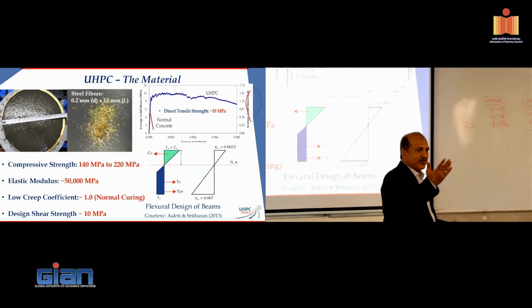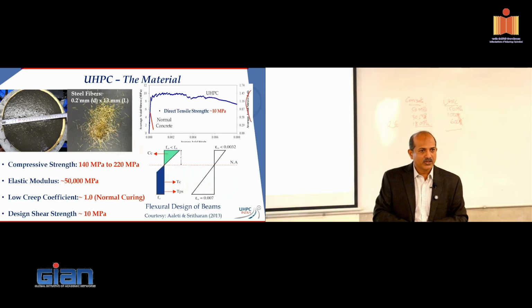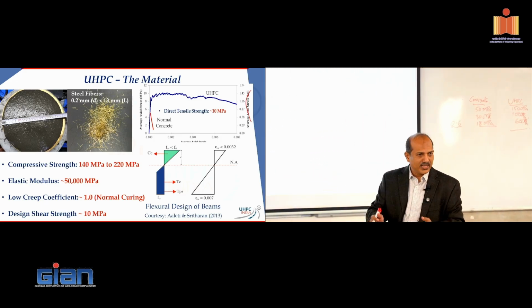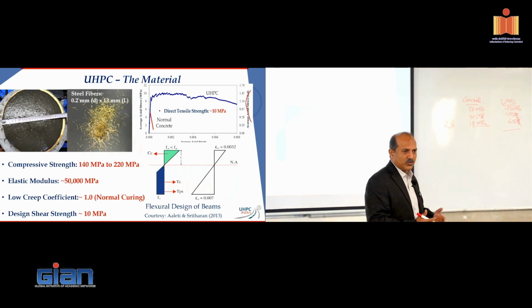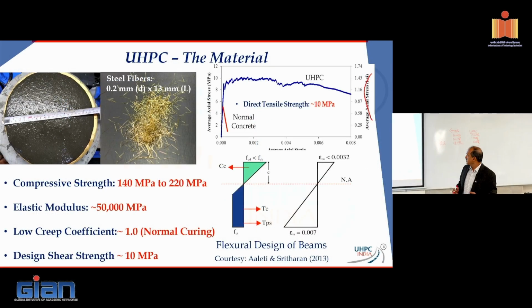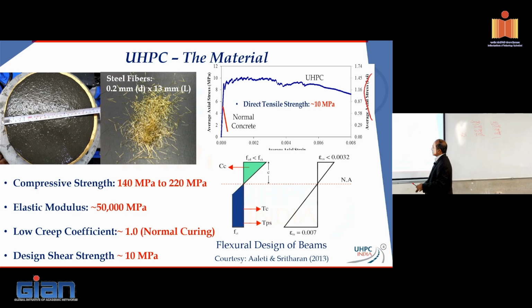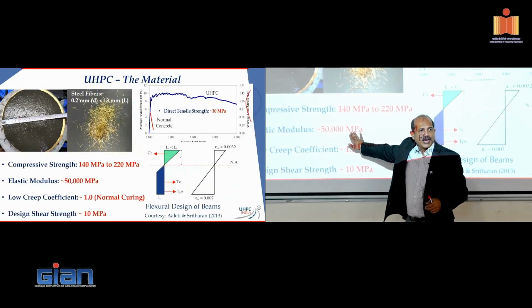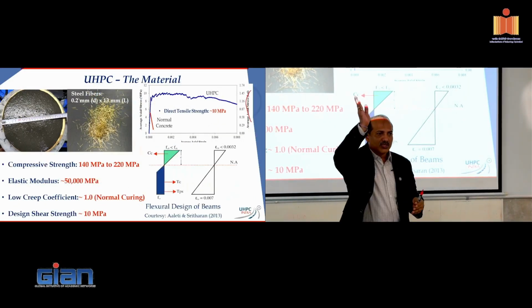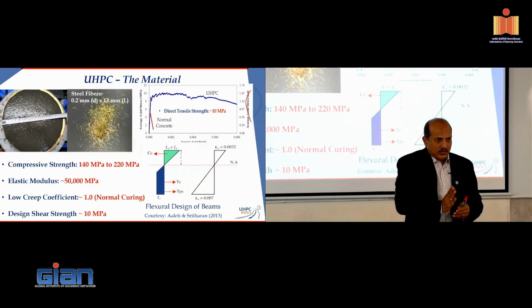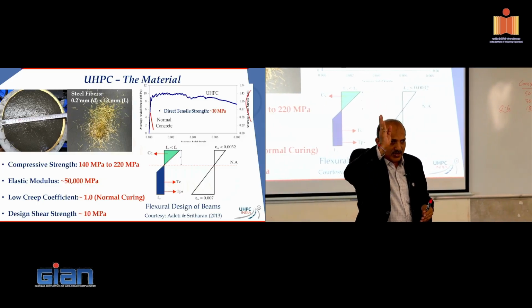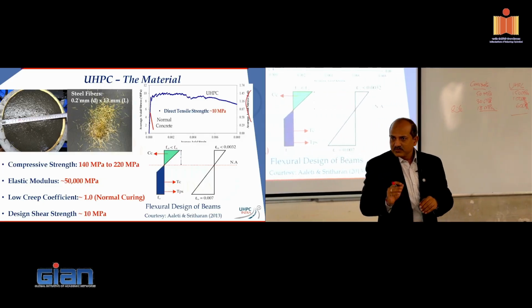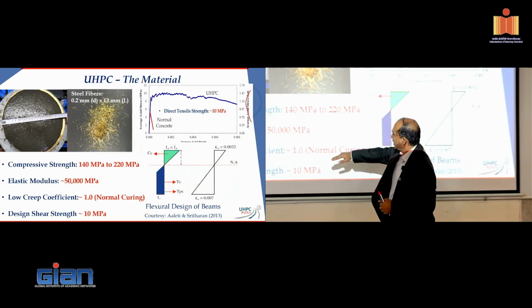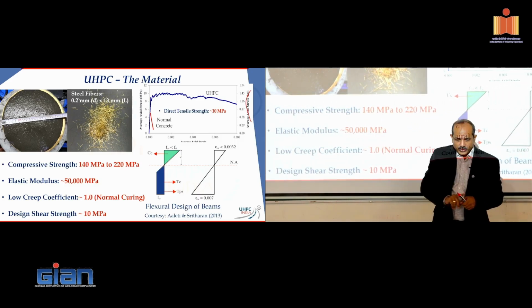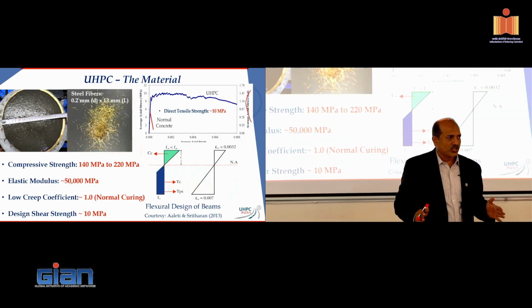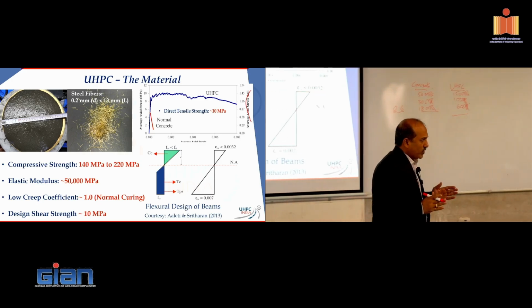You have a 50 MPa column versus a 150 MPa column, you're going to get a reduction in size, and there's nothing else to look at. So that's a very direct advantage. Elastic modulus is generally high. It's not following the same route as a concrete out there because it doesn't have coarse aggregate. At some point, you're going to be right over there in typical construction level UHPC.